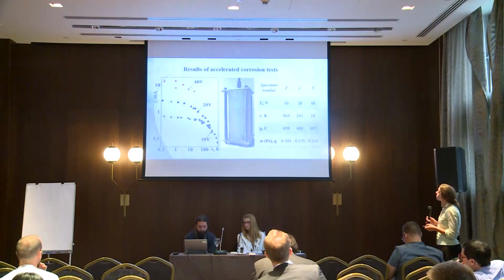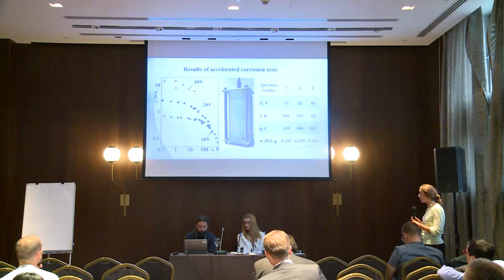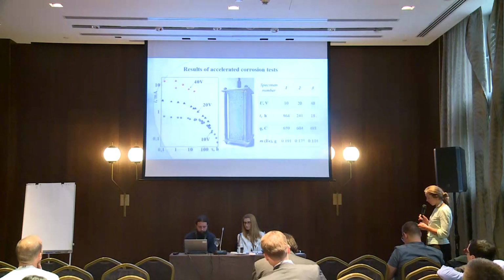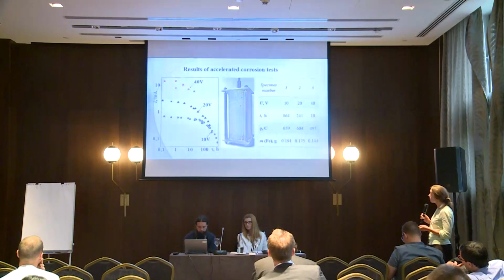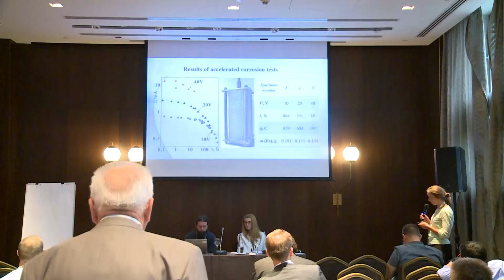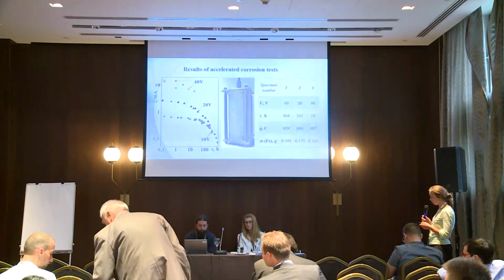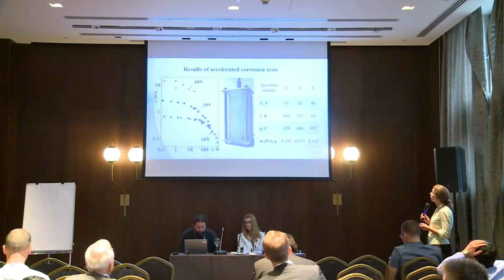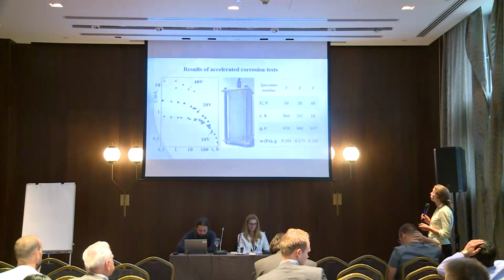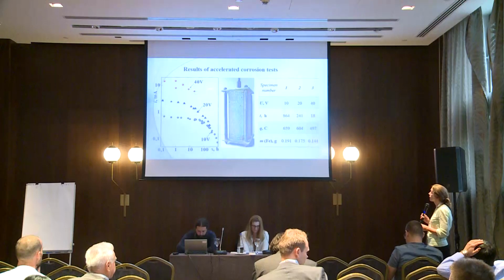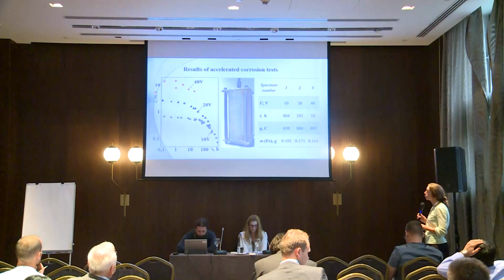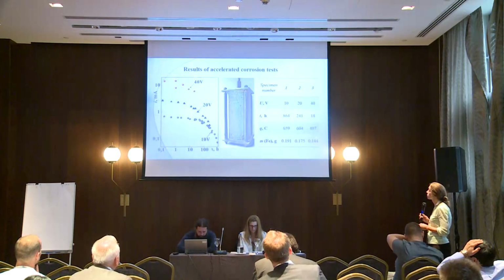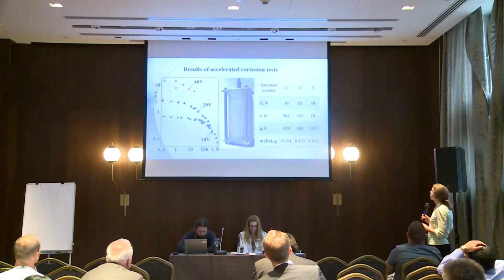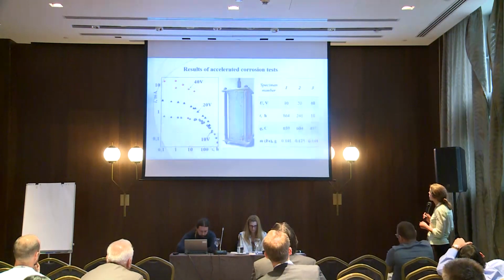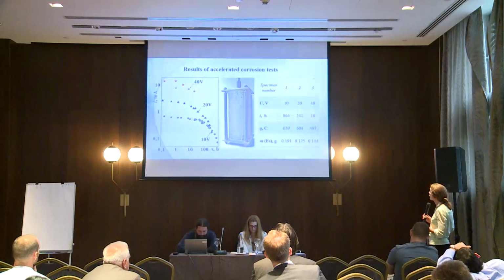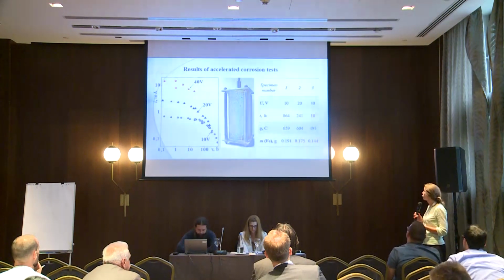So let's go to the results of accelerated corrosion tests. As I have said, we used constant voltage of different values to provide different intensity of corrosion, and the main observations are the following. Under the most intensive polarization, the most intensive corrosion occurs, and the shortest time is needed for cracking. And the higher the voltage, the less amount of corrosion products is required for crack appearance.